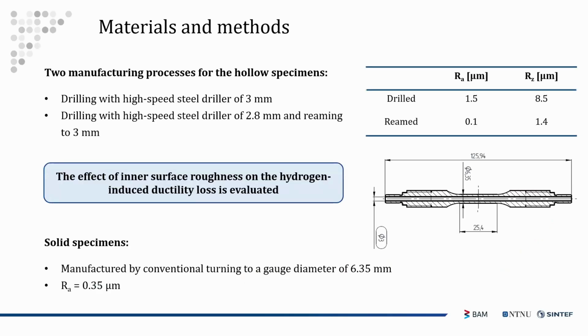So the specimens were manufactured in different ways because we have both hollow specimens and solid specimens. In the case of hollow specimens, we have used two different manufacturing techniques in order to evaluate the impact of inner surface roughness on the susceptibility of the steel to hydrogen embrittlement. The first type of specimen was manufactured by conventional drilling, and the second by drilling and reaming in order to obtain a smoother surface roughness. On the other side, the solid specimens were manufactured by conventional turning in order to obtain the same gauge diameter of the hollow specimen and have somehow comparable results. Unfortunately, we weren't able to obtain exactly the same roughness of the reamed specimen on the external surface of the solid ones, but we tried our best to achieve a similar surface roughness in order to have comparable results.